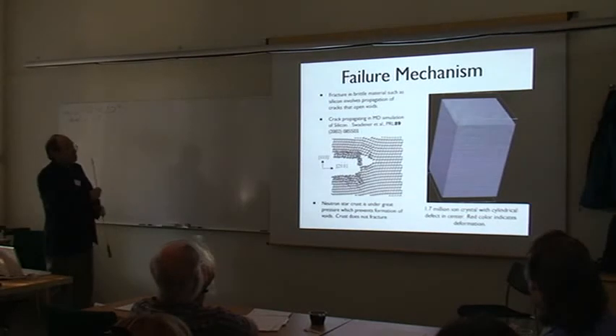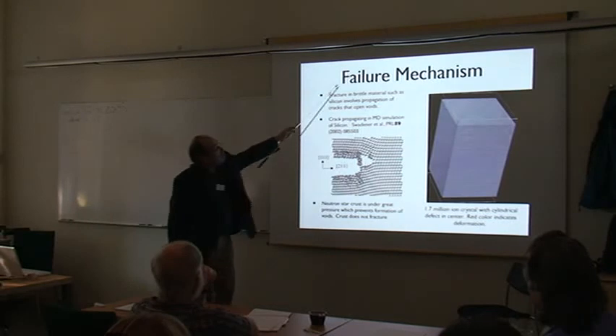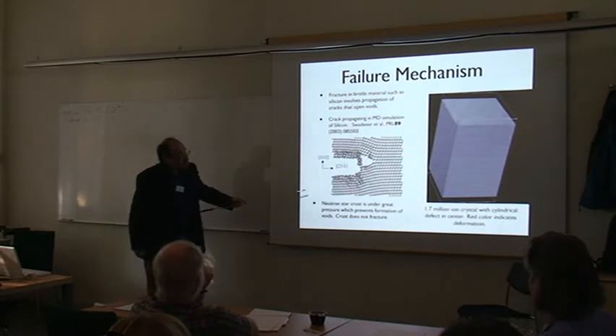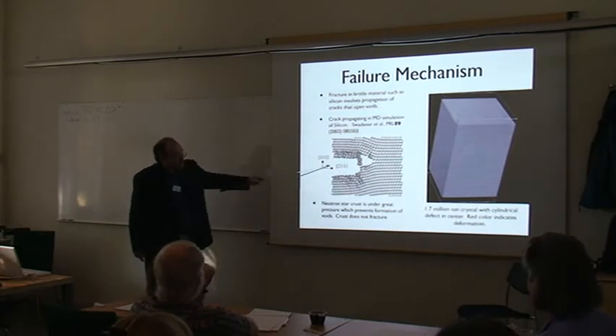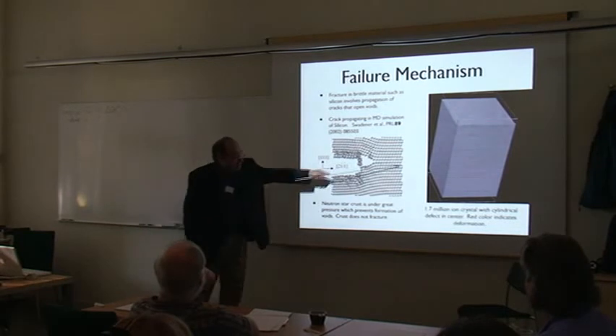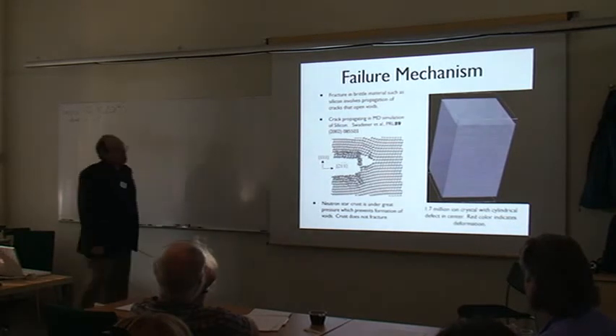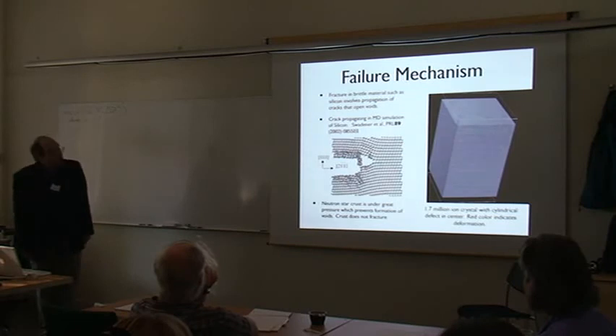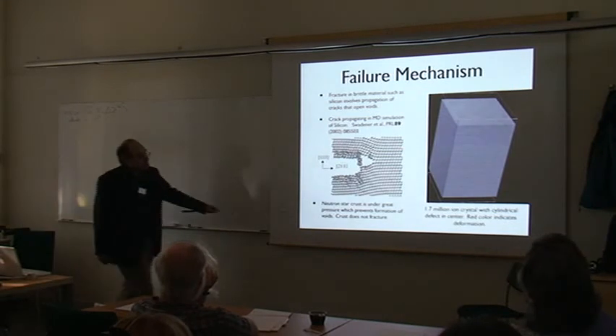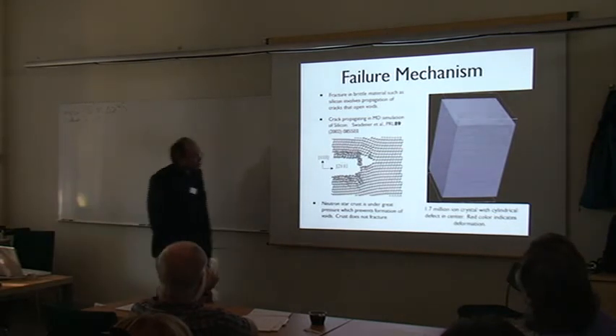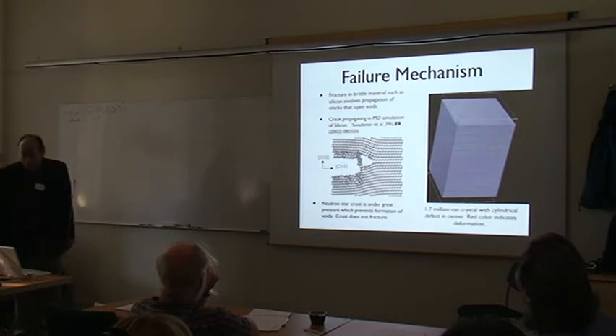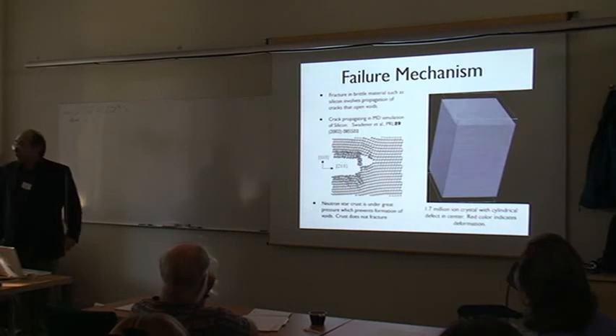Just a couple quick movies. How does it fail? A normal solid like silicon actually fractures—you open a void, a crack propagates, and you break the top off. This system is under very high pressure. The pressure prevents the formation of voids, so the crust does not fracture. It fails catastrophically, but it's not a fracture.